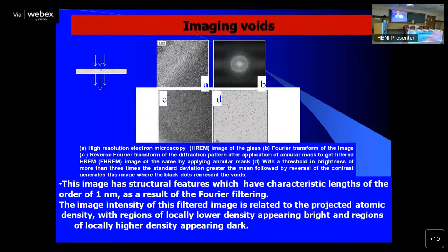And if you take a negative of that, you see these black dots which are actually open voids inside the glass. Again, these types of information were not available before. So you know where these voids are located, and we found that these voids are located at the end of the medium range order domain.